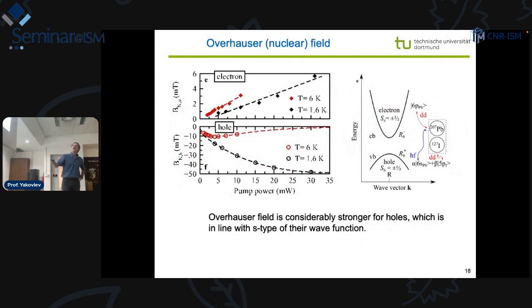So what we find out in this experiment is this dependence of the effective nuclear field for the holes and for the electrons, increasing with the power. We have an external magnetic field of 100 millitesla, and the nuclear field for the holes is minus 50 millitesla. And for the electrons, it's about an order of magnitude smaller. And we understand why, because it's really a specific of the perovskite materials that the valence band is contributed by the s orbitals of lead. It has stronger hyperfine interaction with the nuclei, and in the conduction band, this hyperfine interaction is weak.